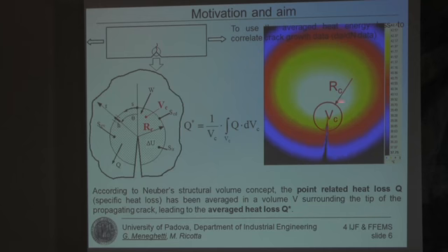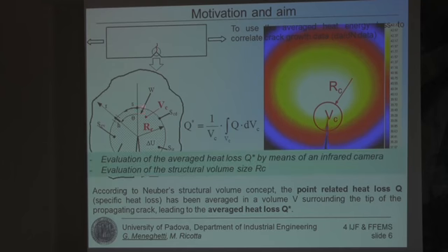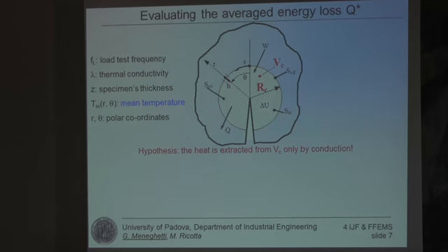We have to define the size of the structural volume, and we have to define the procedures to evaluate the average heat energy. So now we look at these two problems: the evaluation of the average heat loss, Q star, starting from temperature measurements performed in the laboratory, and then the evaluation of the structural volume size RC, because we have the volume size here in our fatigue damage parameter. Now, starting from the first point, the problem is like this. We have a crack, and the first hypothesis is that the heat is extracted from the structural volume only by conduction.